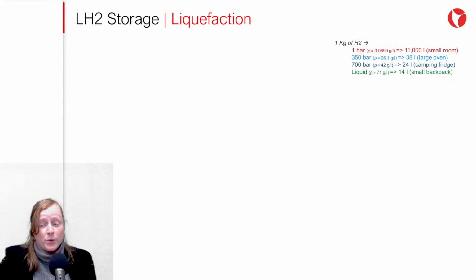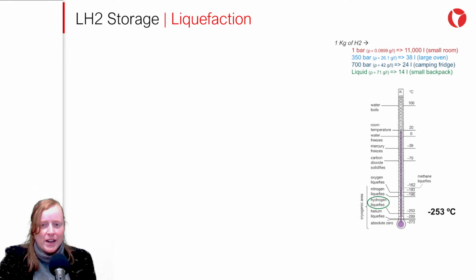This is the comparison between gaseous hydrogen at different pressures that we saw previously, now with liquid hydrogen added. We can see that 1 kilogram of liquid hydrogen occupies only 14 liters compared to the 24 liters it occupies when compressed at 700 bar. To bring hydrogen to a liquid state, however, the temperature must be greatly reduced until it reaches negative 253 degrees